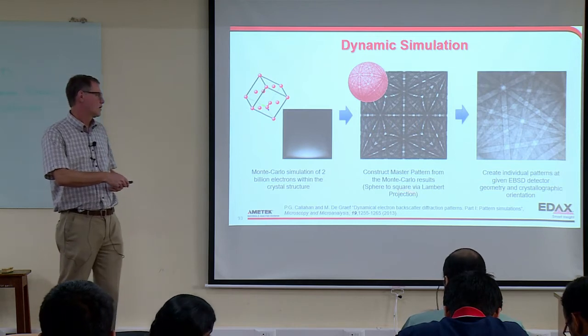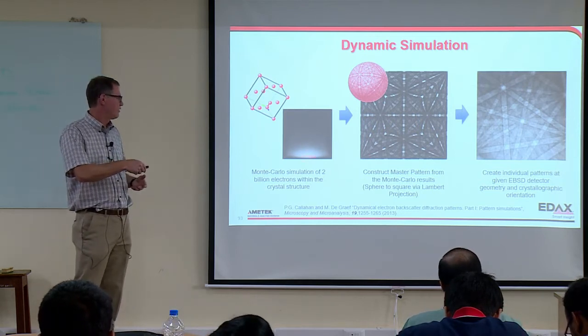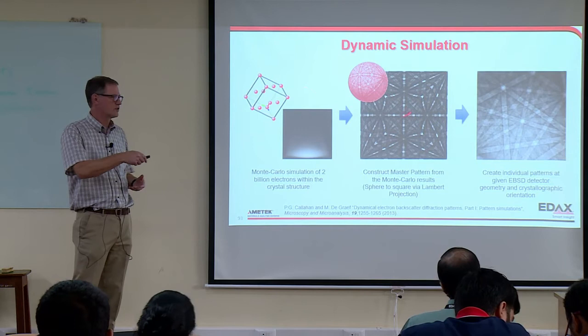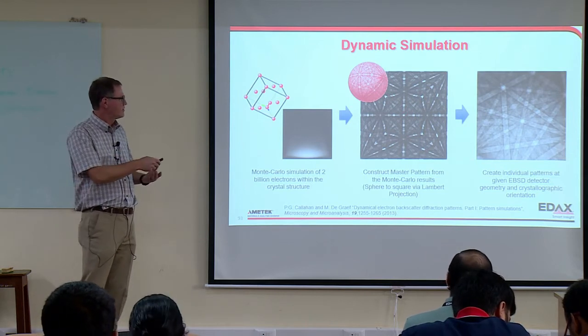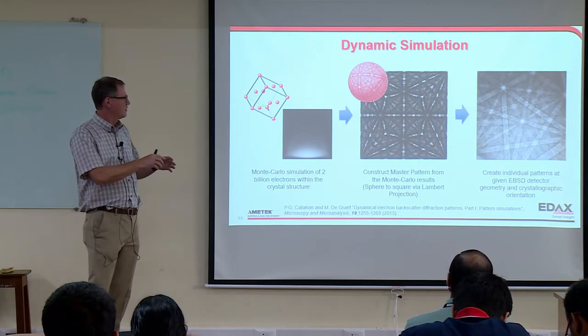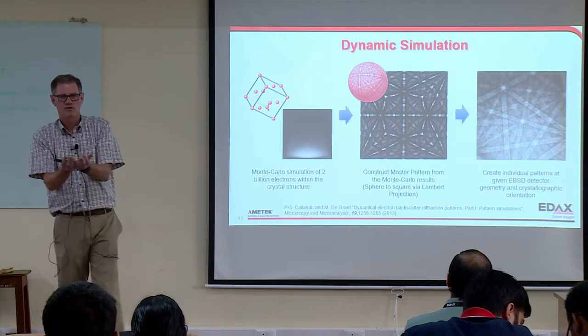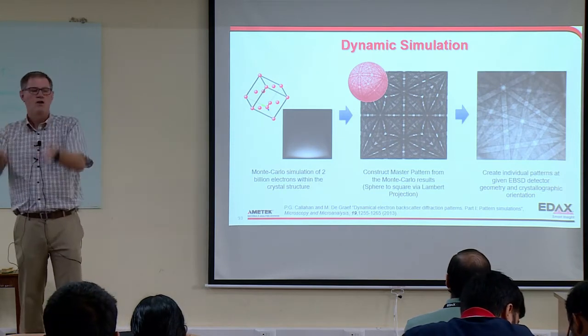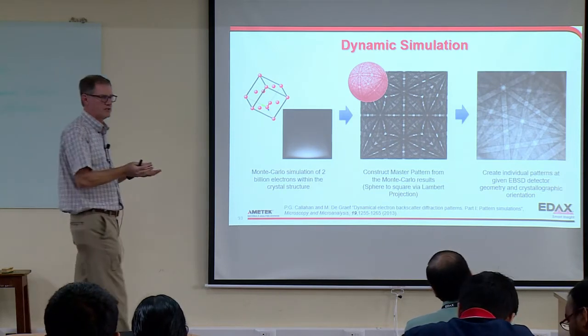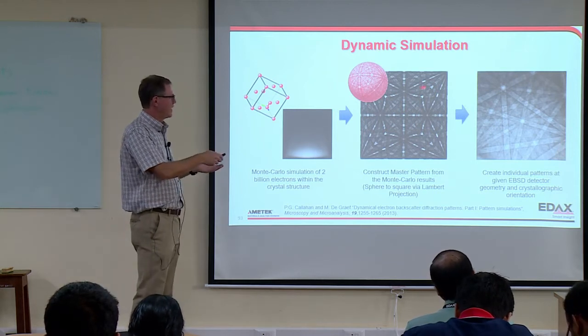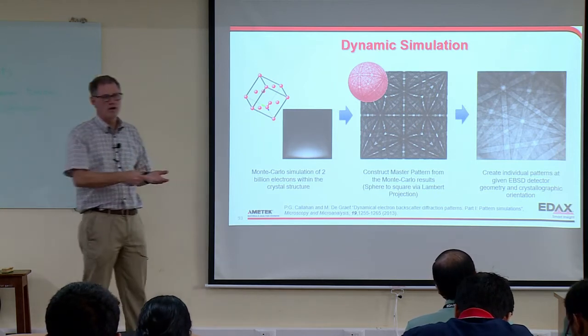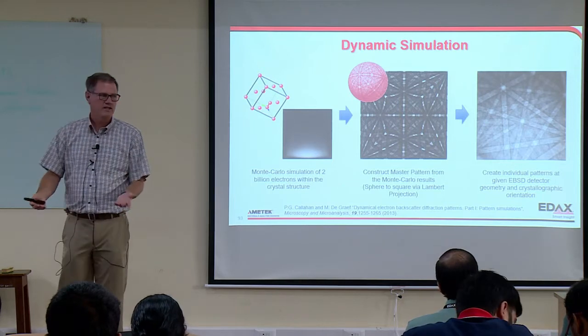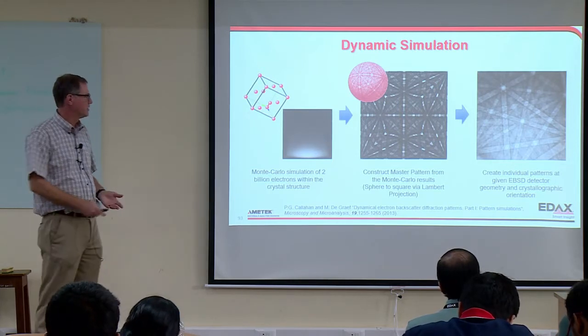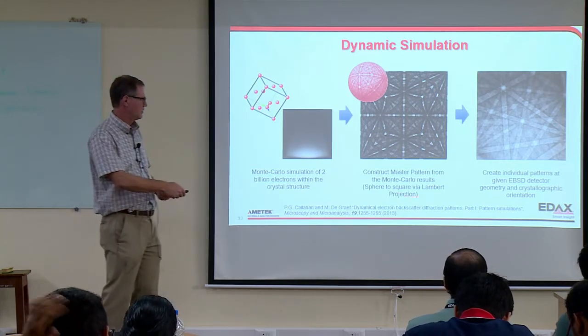And then we construct what's called a master pattern, and we really take into account now these electrons with the crystal structure. And the idea of this is we calculate the diffraction pattern over the sphere. So for all orientations, we know what the diffraction pattern looks like. We'll take that and we project it onto a square, because computers like square arrays, and we're concerned about speed, and it's hard to work with the sphere. It's called a Lambert projection.